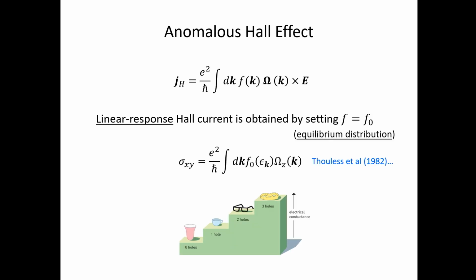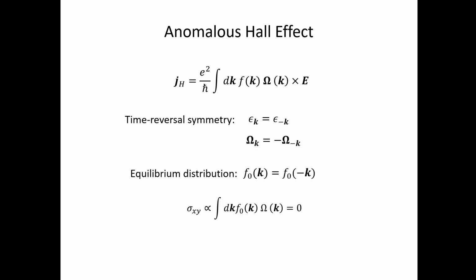Okay. So now at the level of linear response theory, when we look at the total current in the transverse direction, we sum the anomalous velocity of all the electrons in the occupied states. And because the anomalous velocity is already linearly proportional to the electric field, to first order in the external field, the Hall current is obtained by just using the equilibrium electron distribution. And this leads to the famous TKNN formula for the Hall conductivity, which is expressed entirely in terms of the Berry curvature of occupied electron states in equilibrium. In the case of a completely filled band, we get an integral of the Berry curvature over the entire Brillouin zone, and that's mathematically guaranteed to be an integer, and that explains the quantization of the Hall conductance without an external magnetic field.